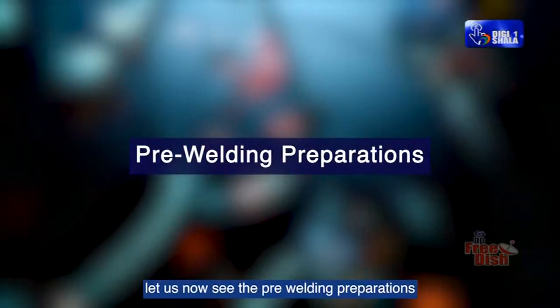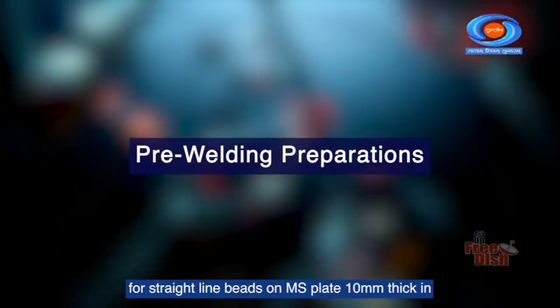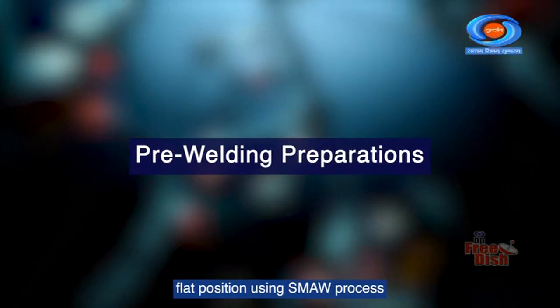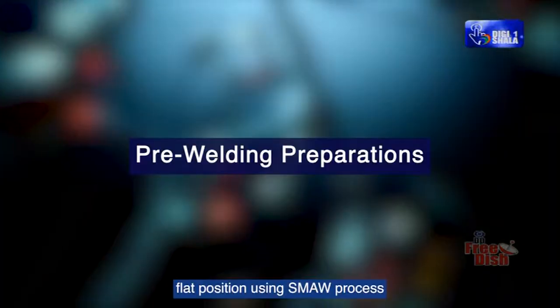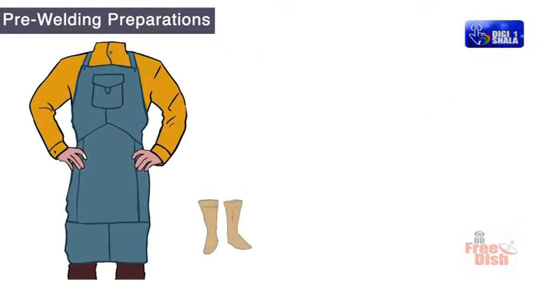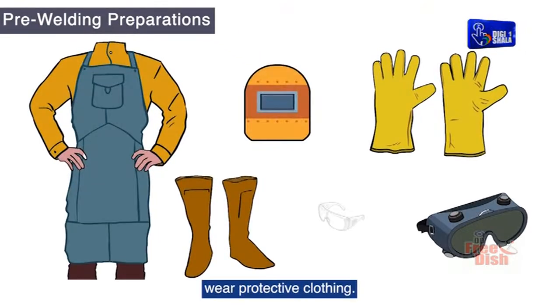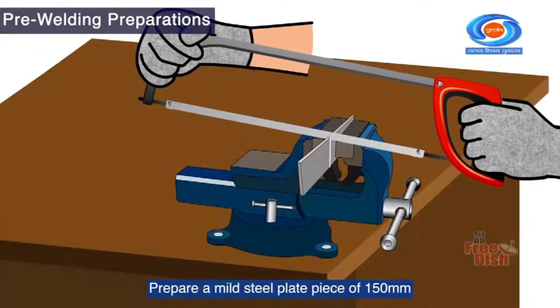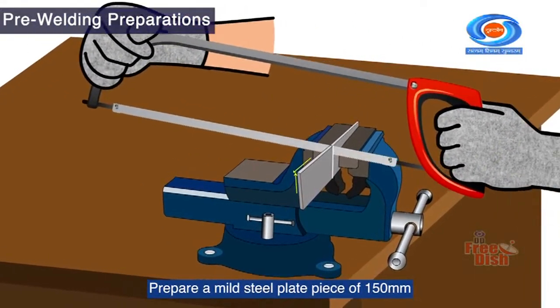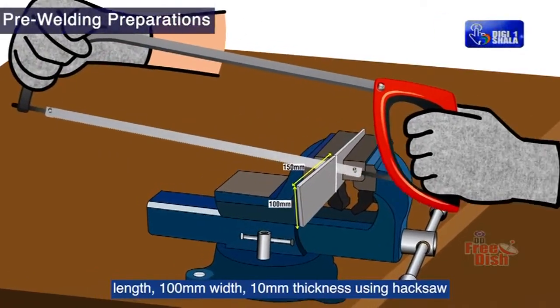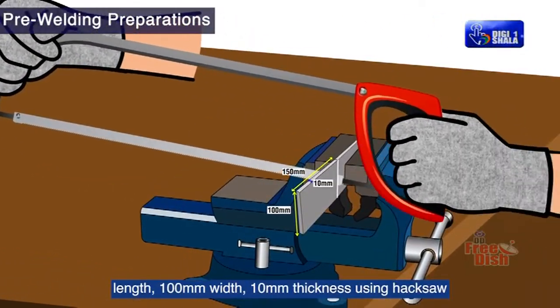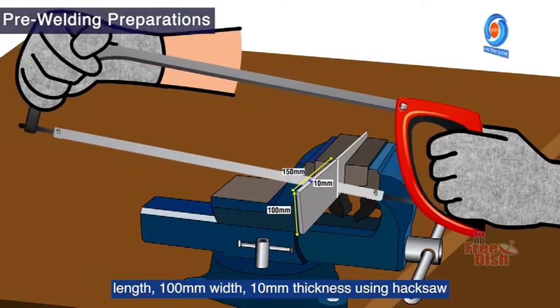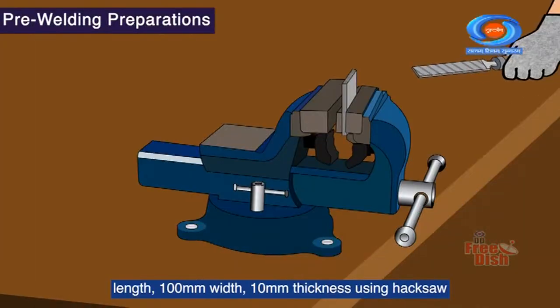Let us now see the pre-welding preparations for straight line beads on MS plate 10 mm thick in flat position using SMAW process. Wear protective clothing. Prepare a mild steel plate piece of 150 mm length, 100 mm width, 10 mm thickness using hacksaw. File the cut plate.